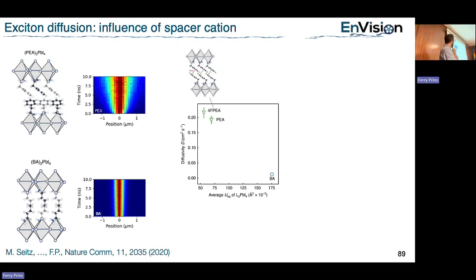You can make a PEA with a fluorine here. Then what happens is not something you really design, but it just happens to crystallize in that way. You get much stronger pi-pi interactions, and your diffusivity is higher. Atomic displacement parameter smaller, more rigid, higher diffusivity.